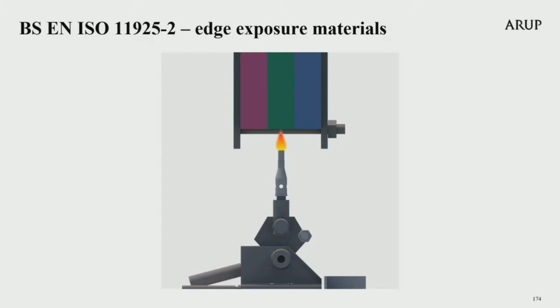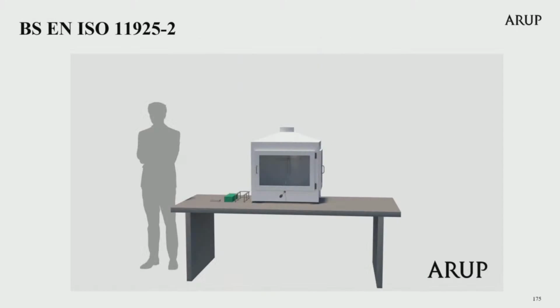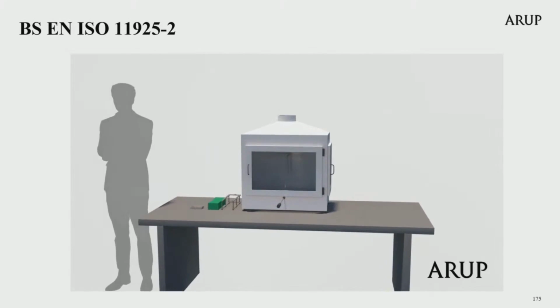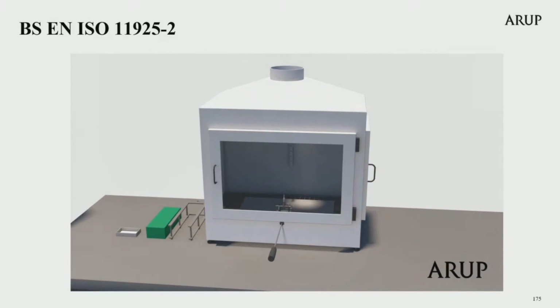For all multi-layered products greater than 10 millimetres, an additional set of tests shall be carried out, with the specimen turned at 90 degrees round its vertical axis and the flame impinging at the bottom edge of the centre line of each different layer. A test is done for each of the layers that make up the sample. I'm now showing you a video of this test procedure.